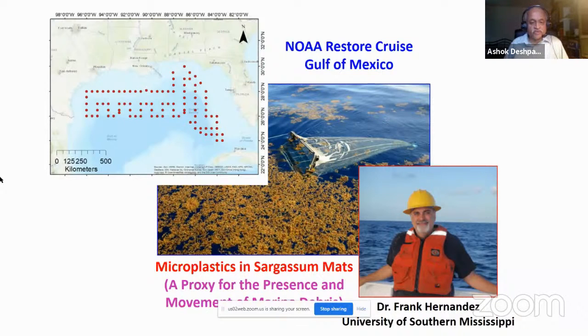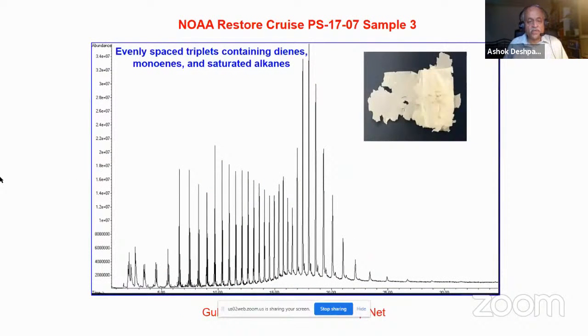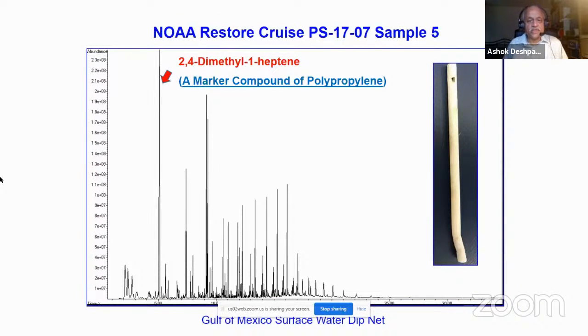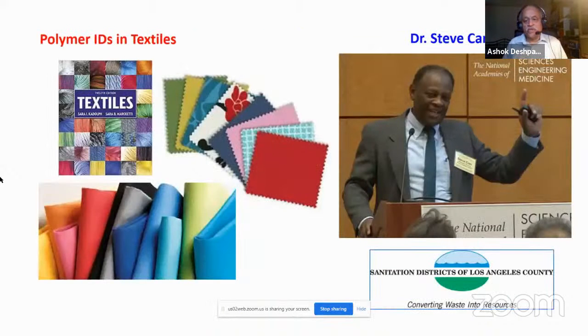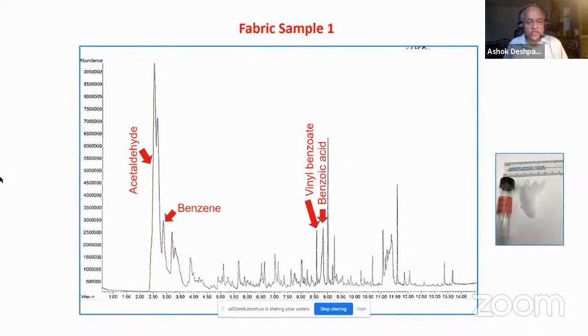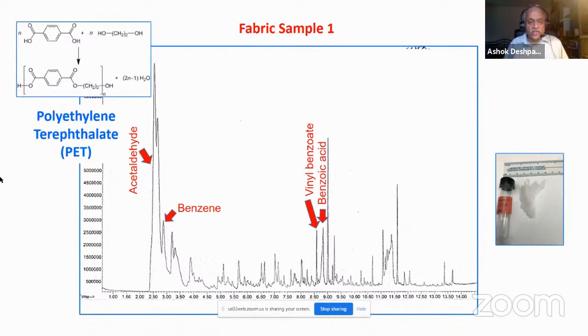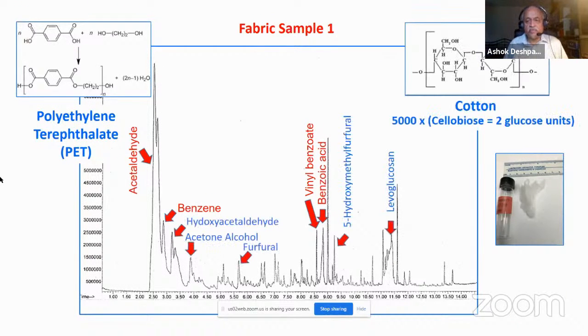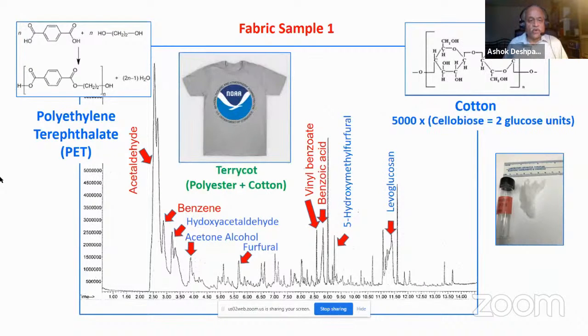Sargassum mats are a proxy for the presence and movement of microplastics and marine debris. The first sample contained a signature of polypropylene. The second sample contained a signature of polypropylene. Dr. Steve Carr from the Los Angeles sanitation districts sent samples of some textile blends. The first sample had a signature of polyethylene terephthalate (PET) and also had a signature of cotton. So we called it terrycot or blend of polyester and cotton.